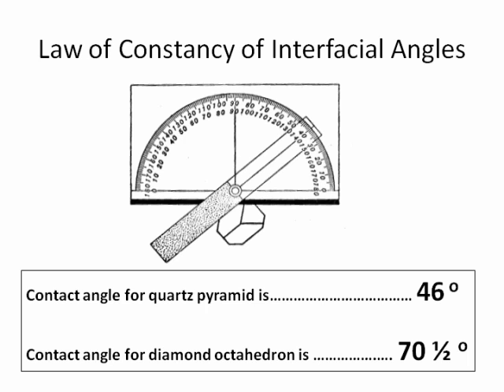So here's how you do it. You get the two faces, you hold it, makes a line. Where two faces intersect, there's a line right there. You get that line absolutely horizontal. You take this and you make it absolutely vertical. You put the black edge down on one side, and then you slide it right to the center, and you put the plastic edge down on the other side, and then you read what angle is that, and find out if it's 70.5. If it's 70.5, we are going to call the press right after we're done and have them come and take a look at this, right? Otherwise, if it's 46 degrees, it's a fake, right? Let's go to the next slide.